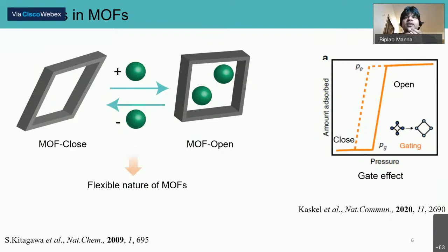As you know, a crystal cannot be soft or elastic. But in recent years, maybe 10 years back, it has been shown that a microporous crystal structure can be deformed with intake or release of guest molecules, as the schematic shows, the shape changes. As we initially showed that a deformable structure is very important for molecular recognition, here the closed and open phases are very important for the recognition of some molecules.